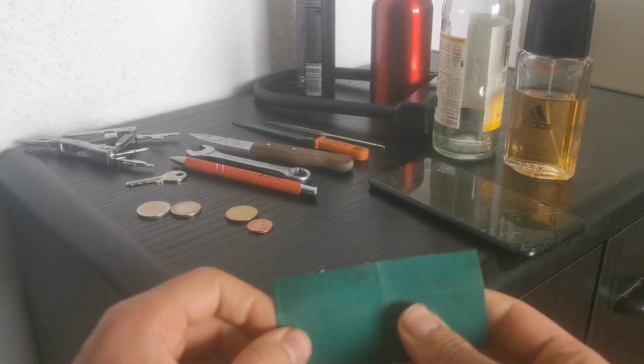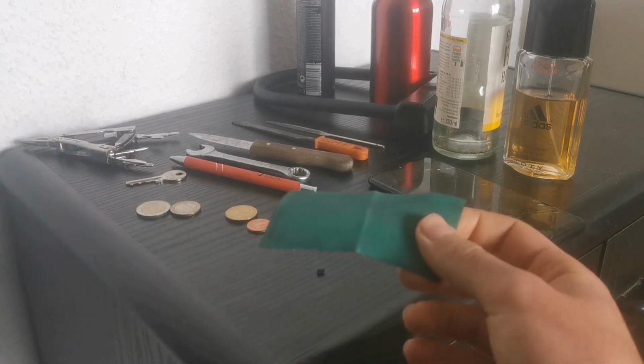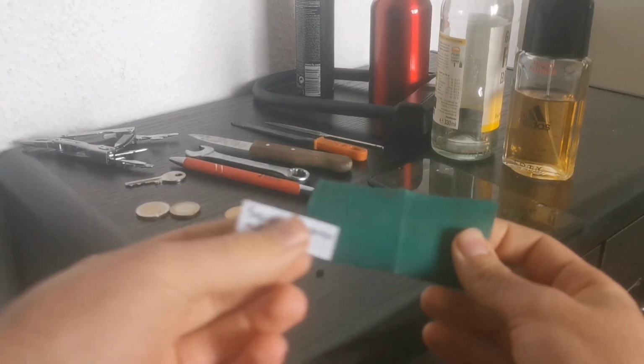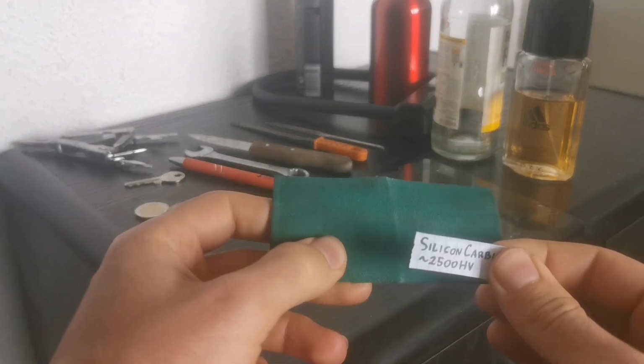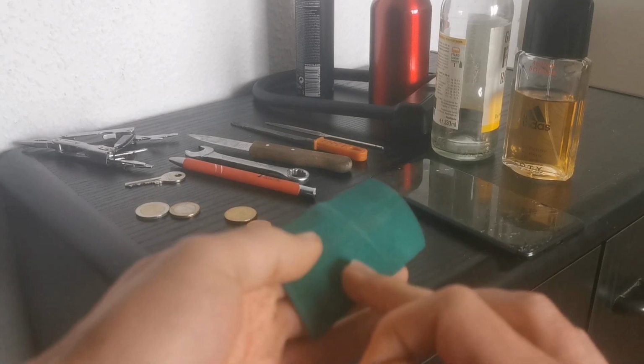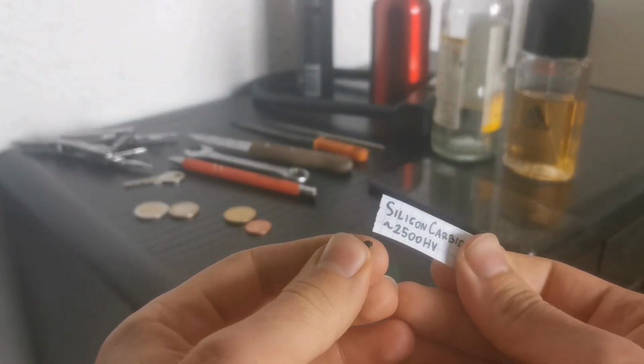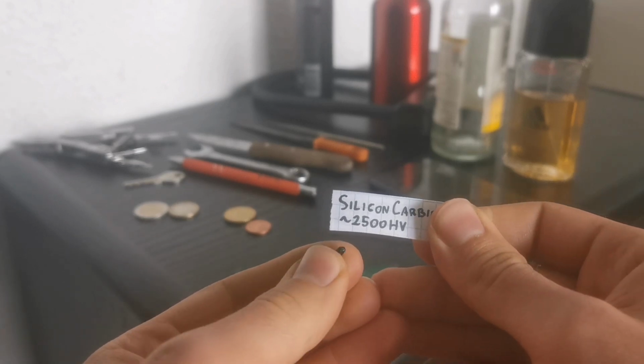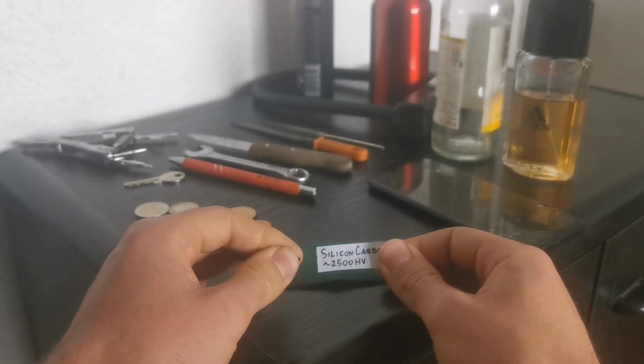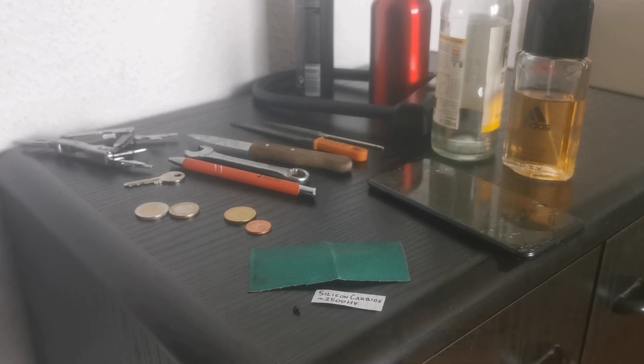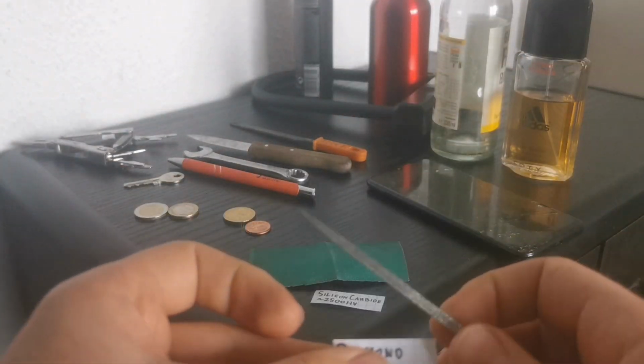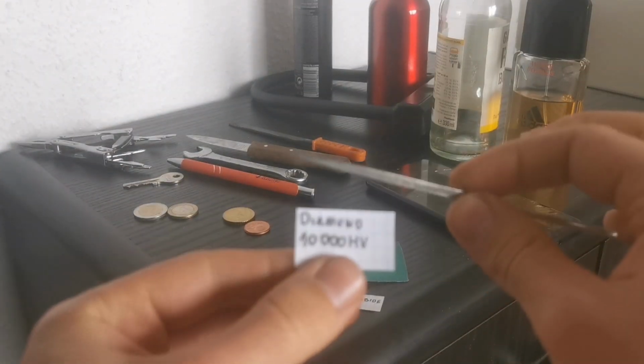Another pick may be sandpaper, namely the silicon carbide that is used for the grains. Here I have a particle of silicon carbide, and it's pretty hard at 2500 Vickers, whereas a diamond on the diamond file has around 10,000 Vickers.